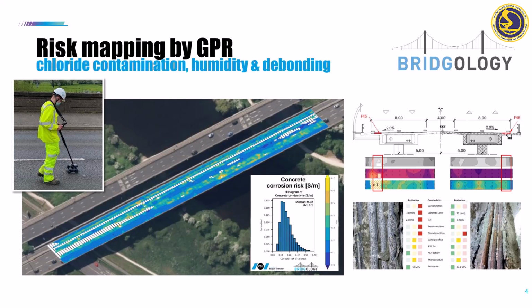And these damage maps can give you an indication of corrosion risk, because the response of the radar signal is linked to the ion concentration in the concrete and therefore to the concentration of chlorides or humidity. On top of that, you get information about concrete cover thickness or areas of delamination, for example, between the asphalt and the concrete, or where you have a waterproofing. So it's a very good method to get very quickly a good overview of the condition of a bridge deck and to identify hotspots of deterioration.